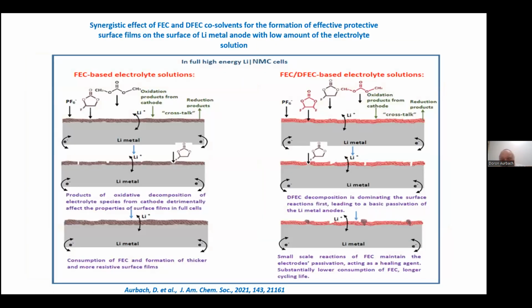So now we can come to this cartoon, and I'll concentrate on the right side. When we have the two fluorinated co-solvents, FEC and DFEC, what we found is the following. The DFEC is the most reactive, so first of all, it is consumed and it forms surface film. But now upon cycling, we have a change in the morphology, we have cracking, the surface films are not always stable, so we have FEC.